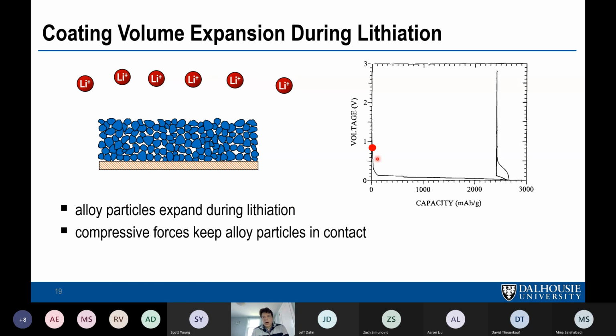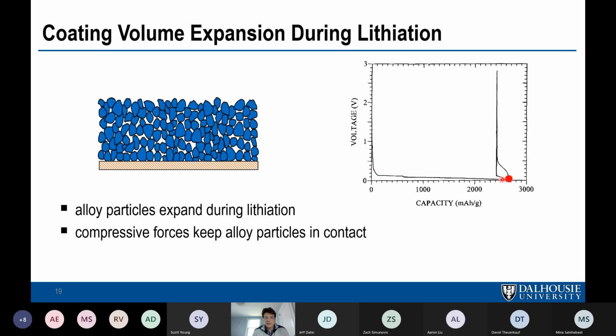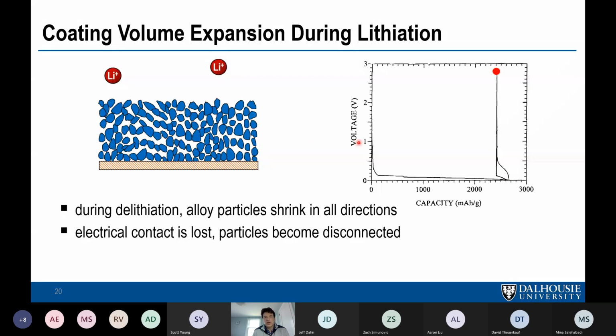And this slide illustrates why you get this kind of behavior in a conventional coating. So here's your coated silicon particles, and here's a copper current collector. And when you insert lithium, this coating is going to expand. And as it expands, of course, you have lots of compressive force inside the coating, and that keeps everything in electrical contact, so that when you're lithiating, this thing's expanding and you can get the full capacity even in a crappy coating. But of course, when you try to delithiate now, all these particles are going to start to shrink, and they're going to pull away from each other, and they'll lose electrical contact. And so as the lithium comes out, they shrink, they become disconnected, and you don't see very much during delithiation.